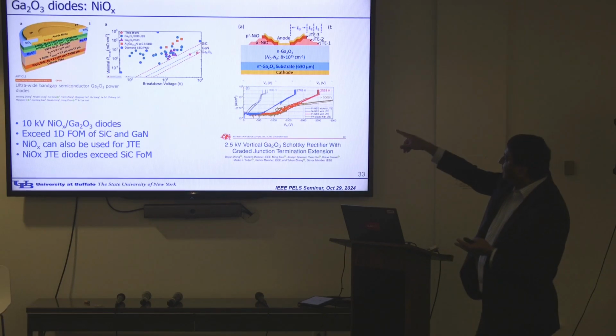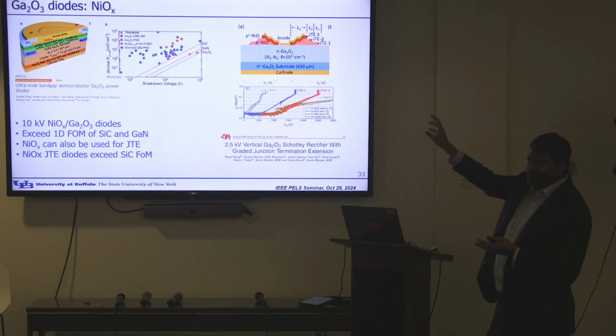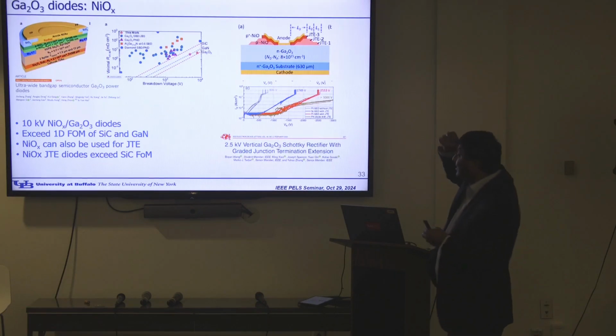And you can see on the center plot here, it's in fact beating silicon carbide. It's reaching the gallium oxide line there, right? This is a single device from single group, but at least shows that you can actually achieve those very high figure of merits on a single device.